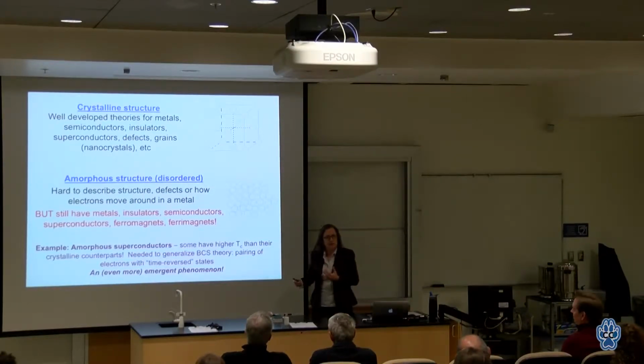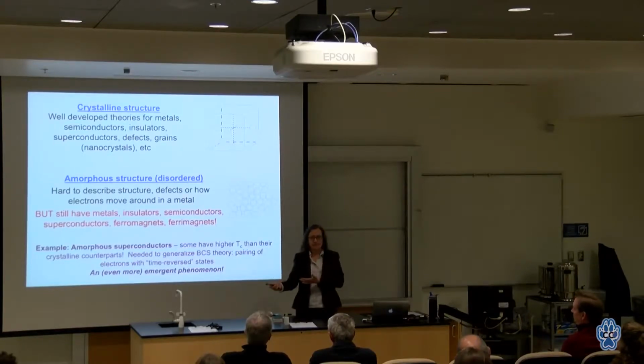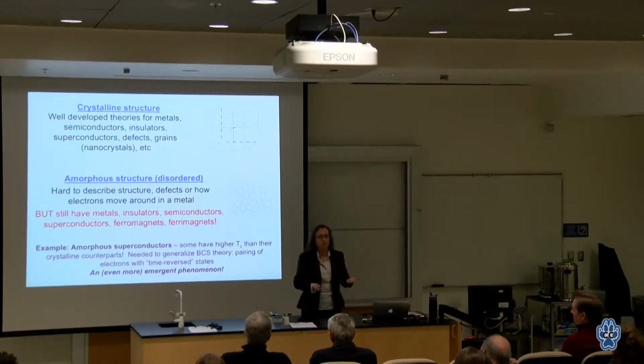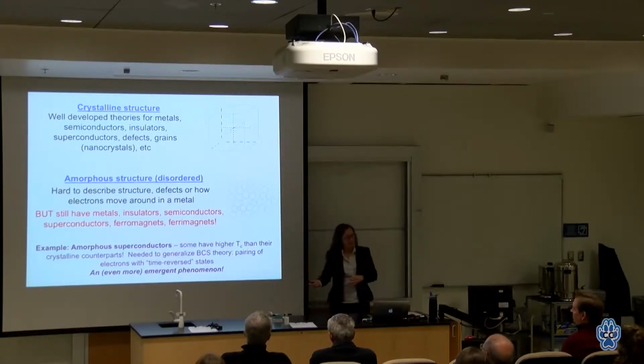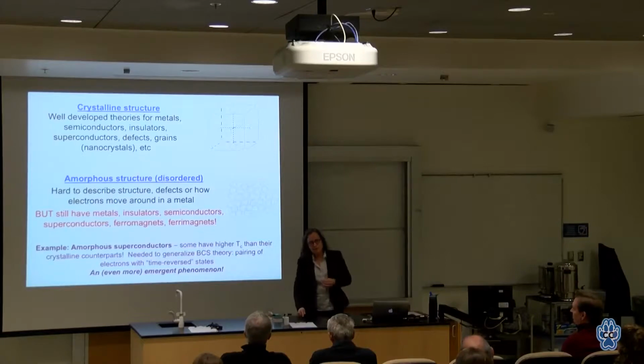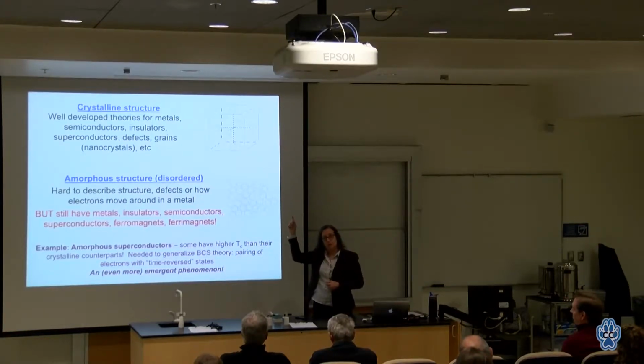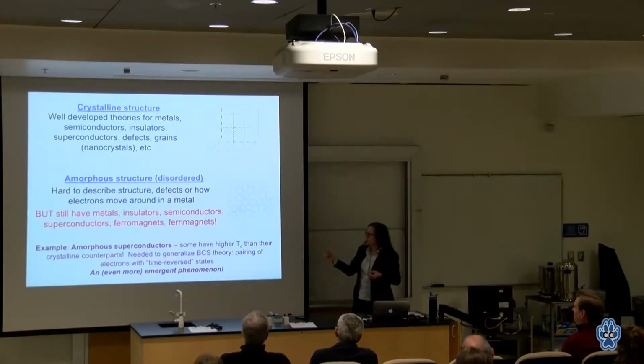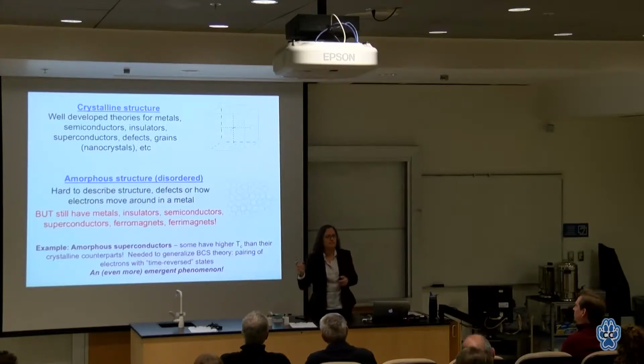Superconductivity is already pretty remarkable, that something can carry electricity without any energy required, no loss, no friction. There are no classical systems that have not just low friction, but no friction. So it's already an amazing idea. But isn't it even more amazing that electrons can travel through a completely disordered, jumbled mess without ever scattering, than that they travel through a perfectly ordered system without scattering? The formal words we tend to use is that superconductivity is robust to disorder. The phenomenon of superconductivity doesn't care whether the system is ordered or disordered.